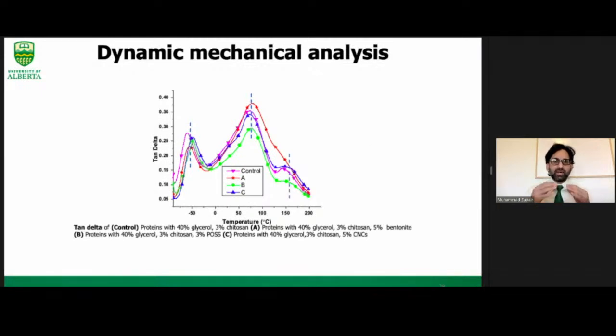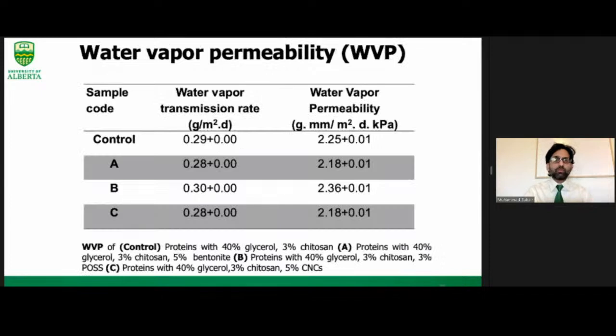So it means that by the addition of the nanoparticles, they undergo more thermal transitions. As a result, by the addition of the nanoparticles, the interaction between the nanoparticles and the proteins has increased. And we can see that in case of nanoparticles, the area under the curve is also improved. It means they go through more thermal transitions and increase their interaction with the proteins, which becomes the reason for the increase in the physiochemical properties of the protein-based films.